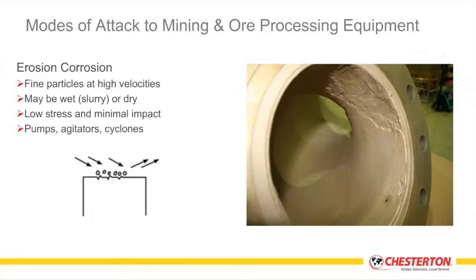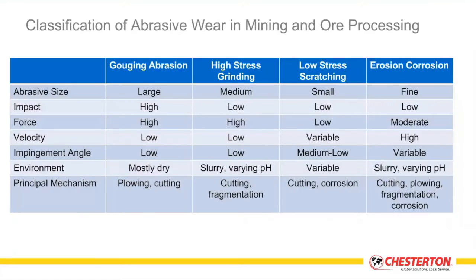And the final area of attack that we sometimes see is known as erosion corrosion. This normally involves much finer particles that have been liberated from the raw ore. They can be present in a wet environment, such as a slurry matrix, or they may be pre-processed in a dry area where they are being conveyed by screw, by a conveying system, or drop chutes. Normally this is a lower mechanical stress and there'll be minimal impact, but we would see this typically in those pumps and agitators and cyclones. And you've been able to identify and see the forms of wear as they occur on each one of these pieces of equipment. So those are your primary modes of attack that we're going to see.